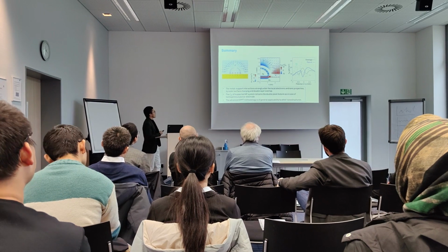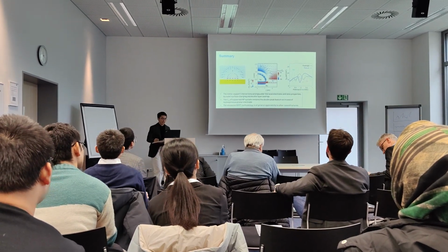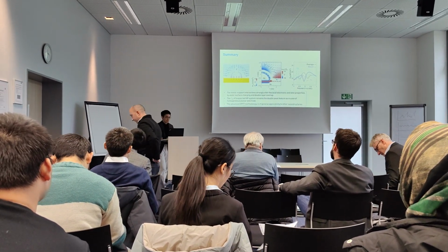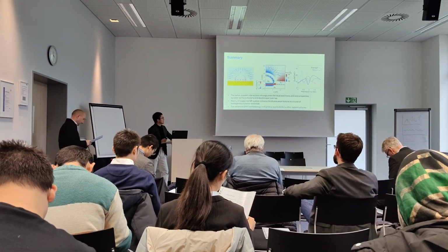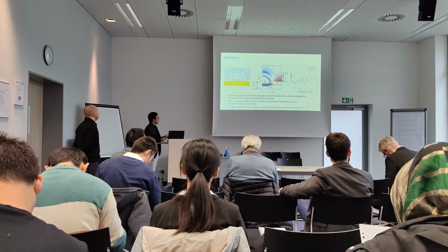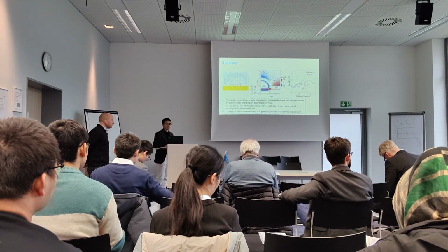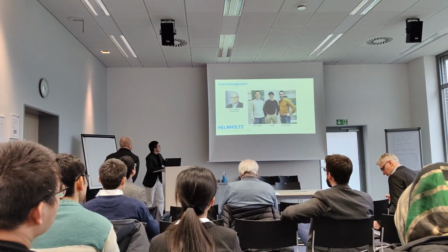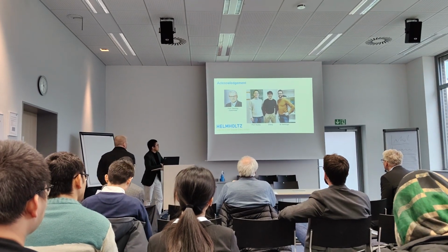Okay, to sum up, the metal support interaction strongly alters the local ionic and electronic properties by outer surface charging and double layer overlap. The differential capacitance of the supported nanoparticle system retains the double peak feature, as in the case of a homogeneous planar electrode. And the advanced DFT methodology is of general applicability to other heterogeneous nanostructures. I thank my colleague Dr. Fatou, my direct supervisor Professor Wang, and Dr. Fermi. Thank you very much.